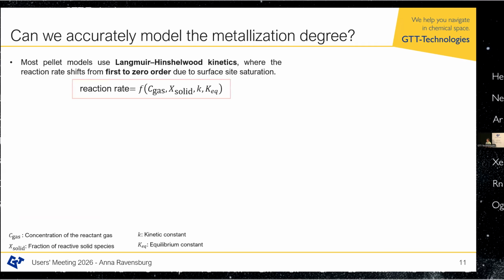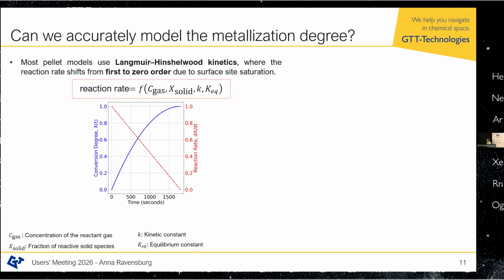Let's start with the microstructure. Most pellets, or pellet models, and I would even dare to say almost all pellet models, use the Langmuir-Hinshelwood kinetics, which means that you have this reaction rate, and it depends on the composition of the gas, of the solid, the kinetic parameters, and the equilibrium constant. And then it looks somehow like this. The blue curve is the conversion degree. So you go again from 0, which would be Fe2O3, to 1, which would be alpha iron. And if you plot the reaction rate, which is the right axis, in red, you would just have a linearly decreasing reaction rate, because it first goes fast, and then it goes always slower. And this is the very easy and first approach to these kinetics.